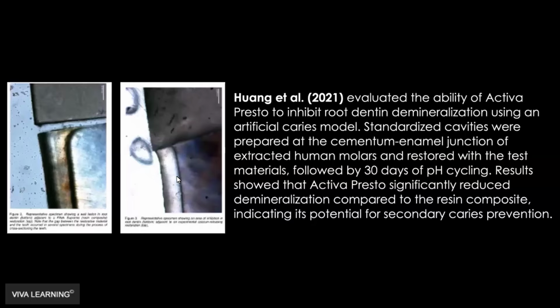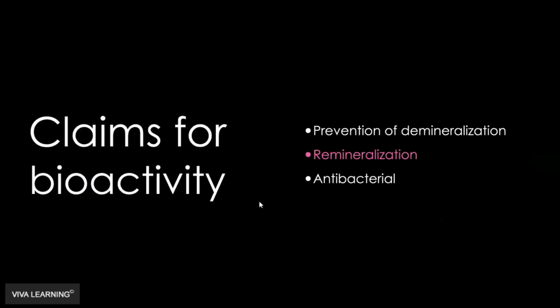Whereas when we looked at the Activa material, the bioactive material, you didn't see any wall lesions. Some of the specimens, you could even see a slight bit of protection, like where there'd be less demineralization near the restorative than away from the restorative material, but at least we saw prevention of wall lesions for sure. So this is more evidence that these can prevent demineralization of surrounding tooth structure.